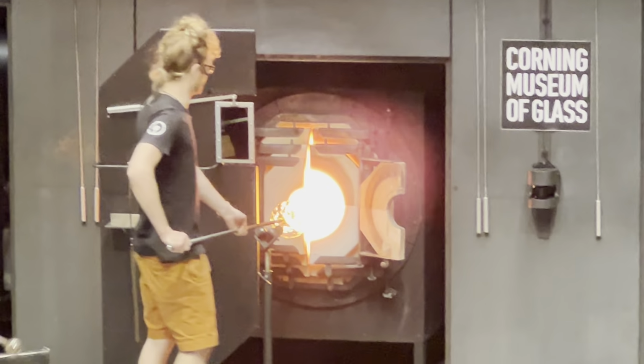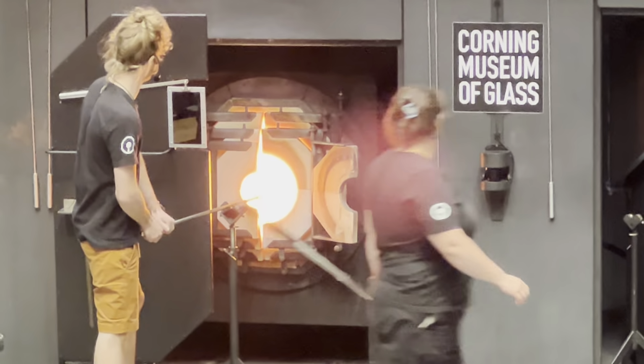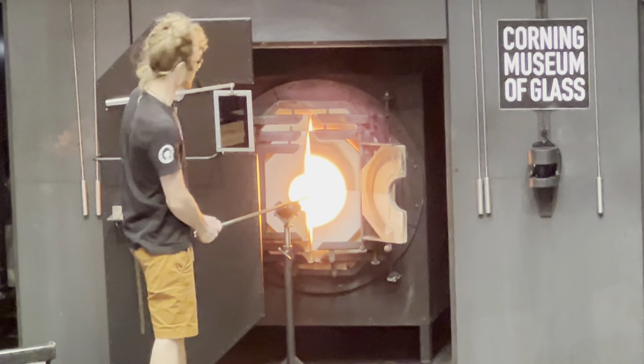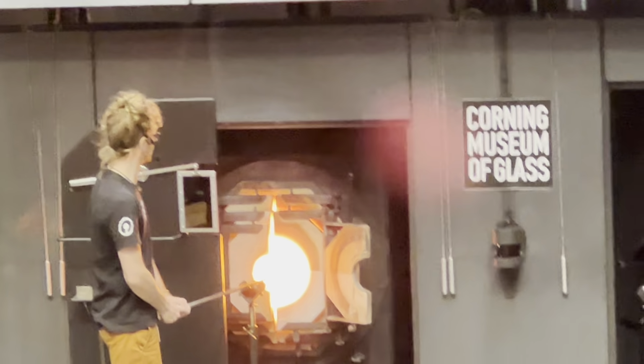To remove the glass from the blowpipe, a couple drops of room temperature water creates thermal stress, creates those little cracks in the surface, and a light tap is all it takes to break the piece free. I say we give Catherine a big round of applause for breaking glass.